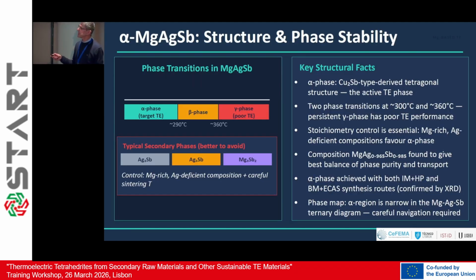So, looking deeper at magnesium silver antimony, it's not so easy to work with this material because it has quite complex chemistry. The phase diagram is not so clean. There are several impurities that can appear and usually appear in your material. And even the 111 compound has several phase transitions depending on the temperature. What we want, the best phase for thermoelectricity, is the alpha phase. But we have one phase transition at 290 Celsius to the beta phase, which is metallic, and then at 360, you get the gamma phase, which is very stable. So it's usually hard to get rid of it when it is formed.